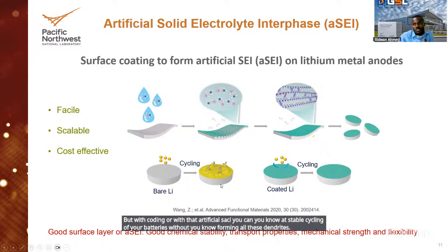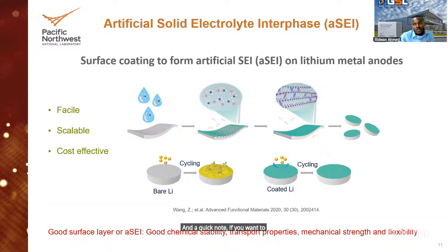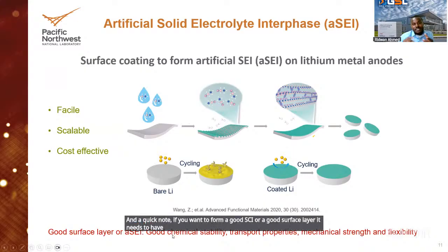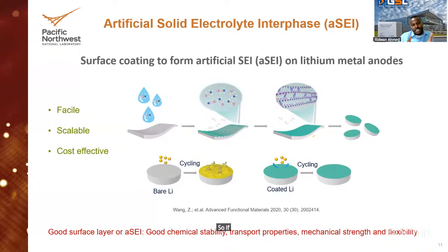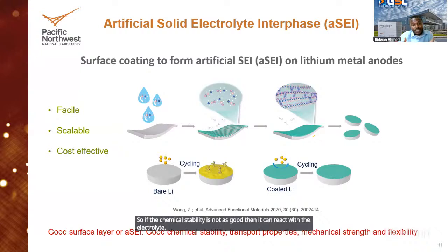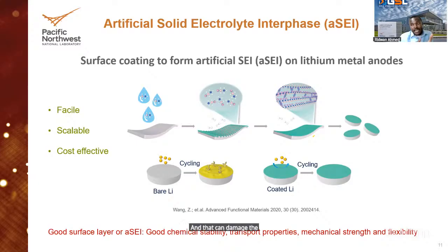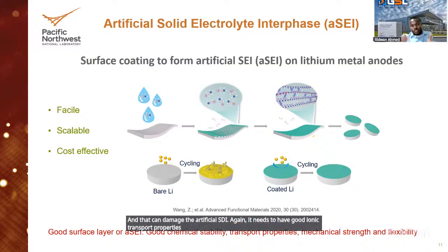As a quick note, if you want to form a good SEI or a good surface layer, it needs to have good chemical stability because it's going to be in contact with the liquid electrolyte. So if the chemical stability is not as good, then it can react with the electrolyte. And that can damage the artificial SEI. Again, it needs to have good ionic transport properties because you still want your lithium ions to be able to go in and out during charging and discharging.